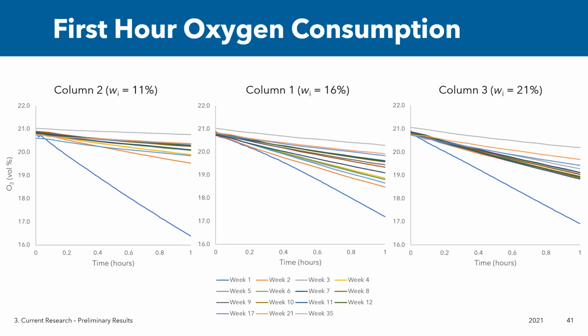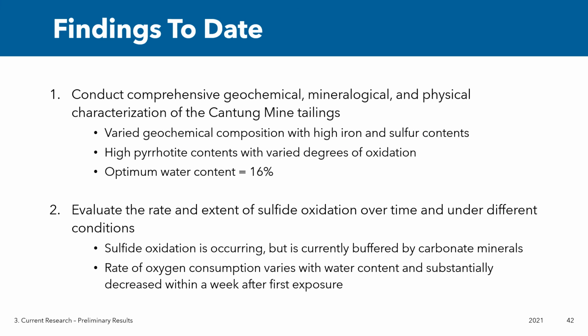For all the columns, pH has remained around neutral, and surface temperature has followed the air temperature. For my first objective of characterization, the main findings include the variable geochemical composition of the tailings with high iron and sulfur contents, the high pyrrhotite contents with varying degrees of oxidation, and the optimum water content is 16%.